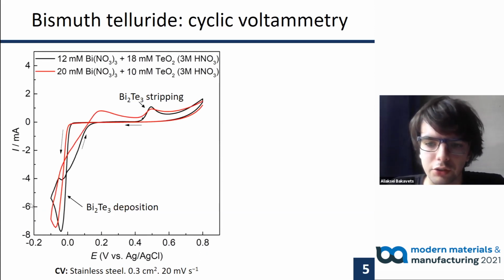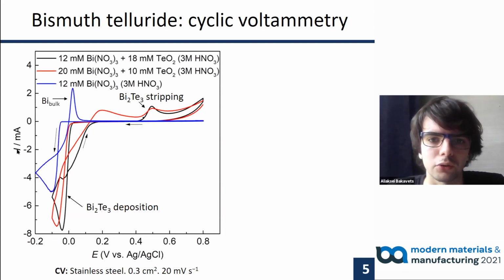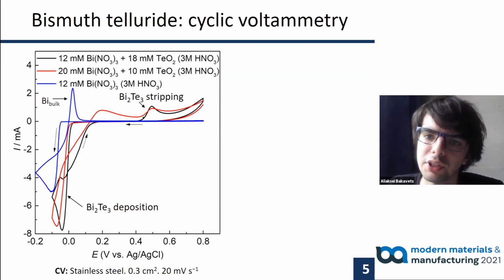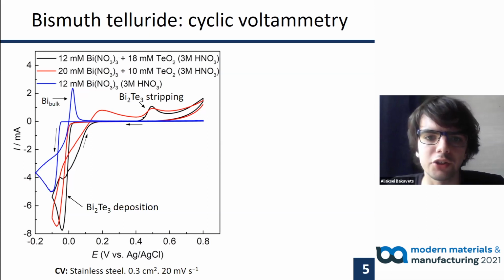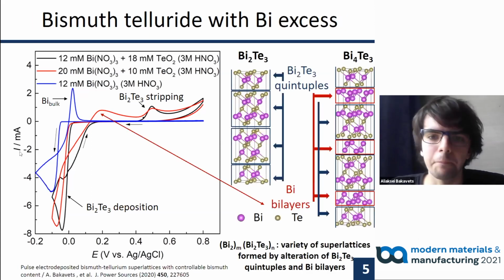With increase in concentration of bismuth cations in the electrolyte used for the electrodeposition, an additional process is observed in the anodic scan. The potential corresponding to this process is intermediate between the oxidation of bulk Bi2Te3 and metallic bismuth. This process corresponds to selective anodic oxidation of the interlayer bismuth in Bi2Te3-Bi superlattices, and the thorough proof of this was presented in our article in Journal of Power Sources.